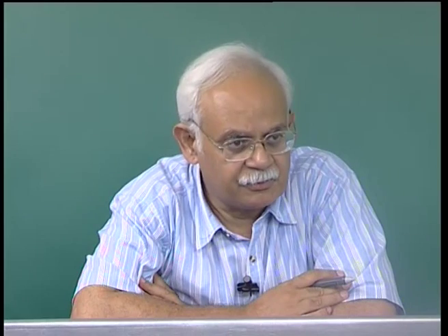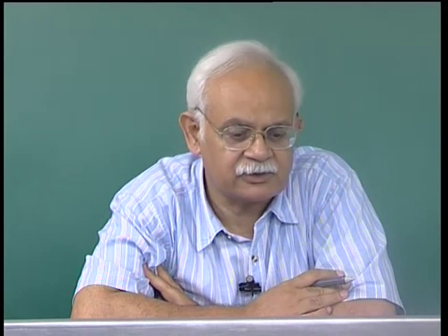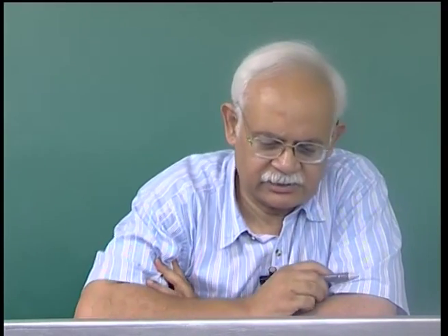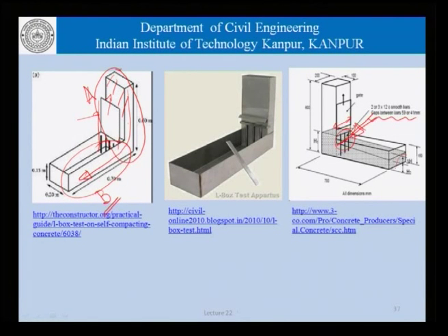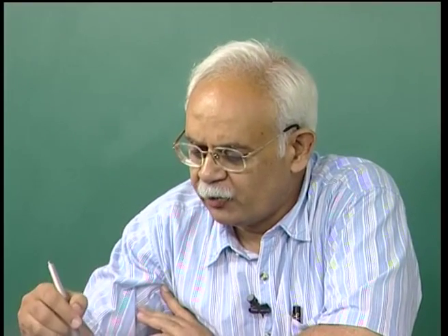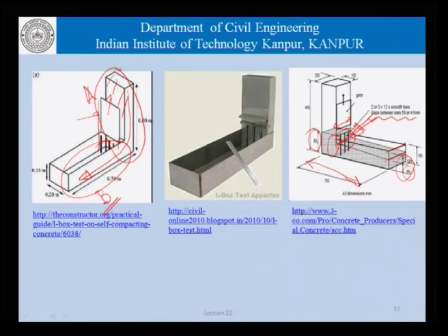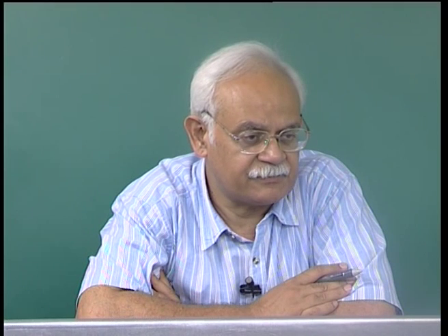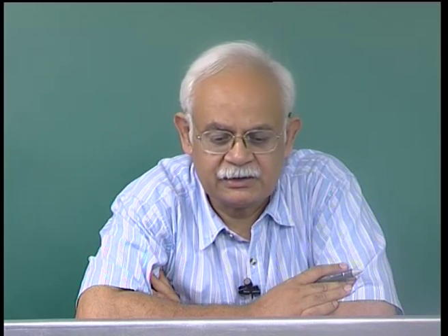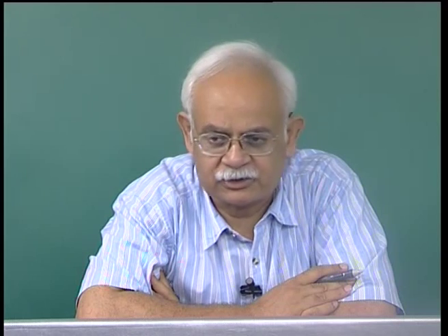So, the kind of measure that would be used as far as testing the L box is concerned, it's largely the difference in this height at these two places. So, H1 and H2, and then there is this delta H. So, if the concrete was to behave as a real fluid, then we would not expect any difference in the height over this length that the concrete is flowing. But since the concrete at the end of it is not really a fluid, there will be a certain amount of difference in the heights at these two places, and that is the difference that we want to monitor and measure as the output from this test, which is called the L box test.